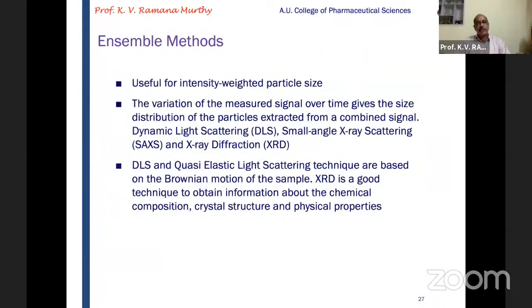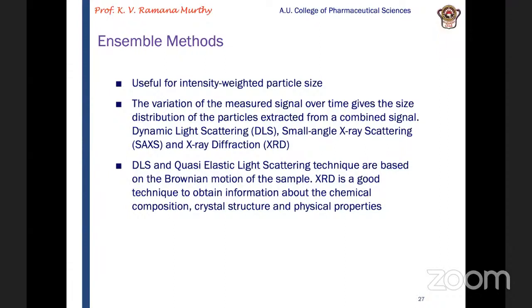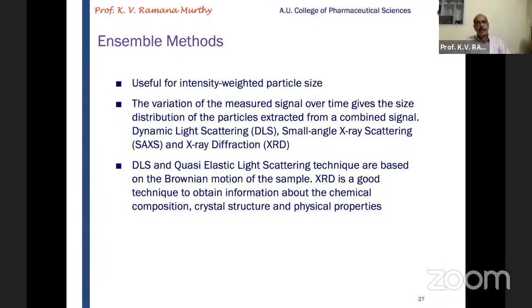The ensemble methods involve intensity-weighted particle size measurements. Here we are not going to count the number of particles, but we can measure the intensity of a specific particle size distribution, and we may be using dynamic light scattering, small angle X-ray scattering or X-ray diffraction. DLS and quasi-elastic light scattering techniques are based on the Brownian motion of the sample, and XRD is a good technique to obtain information about the chemical composition, crystal structure, and physical properties.